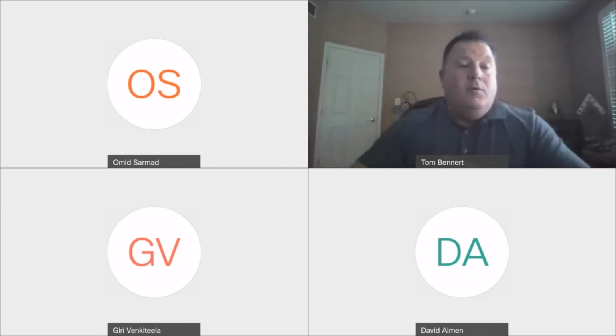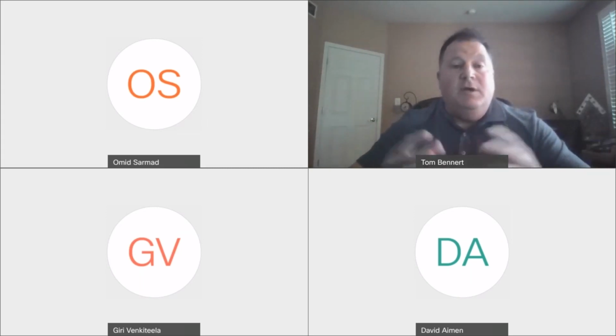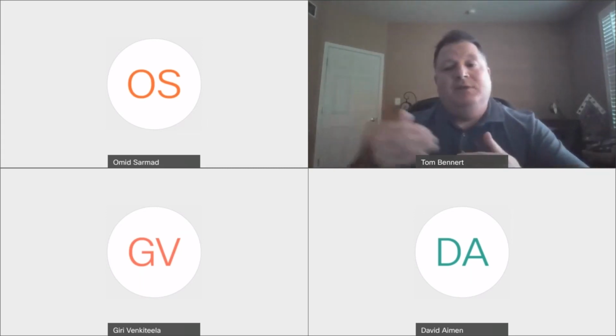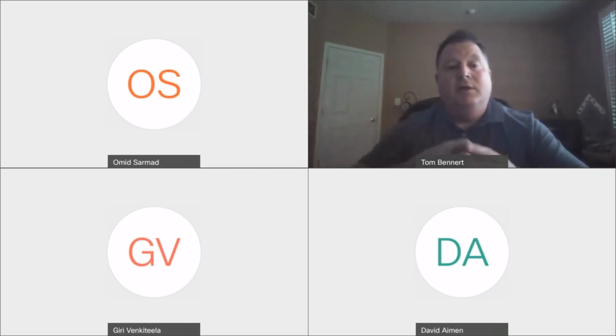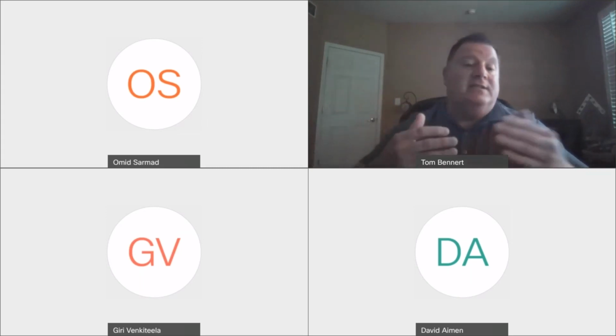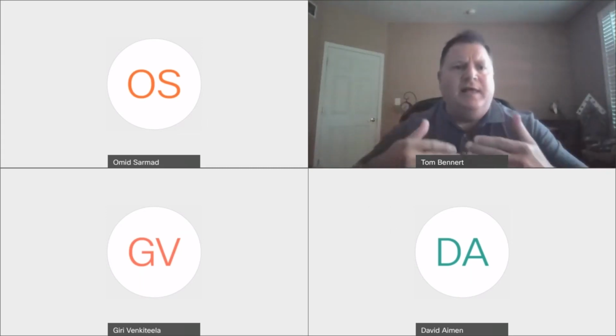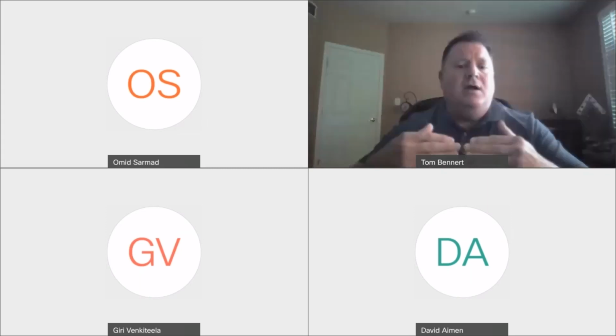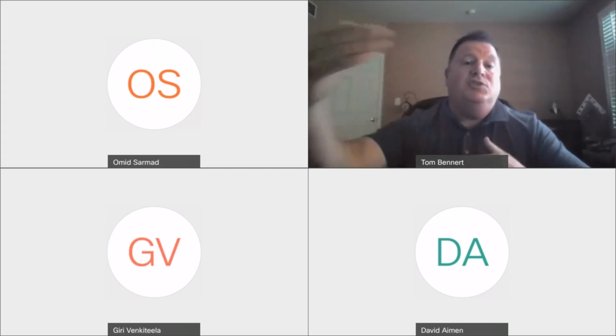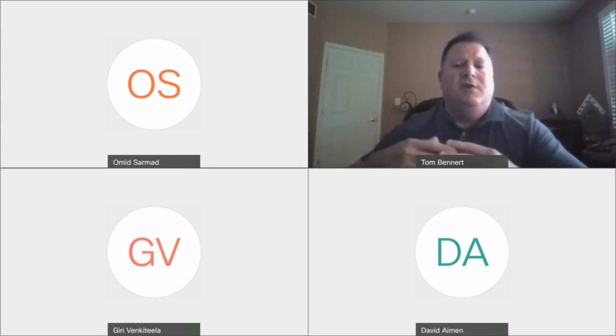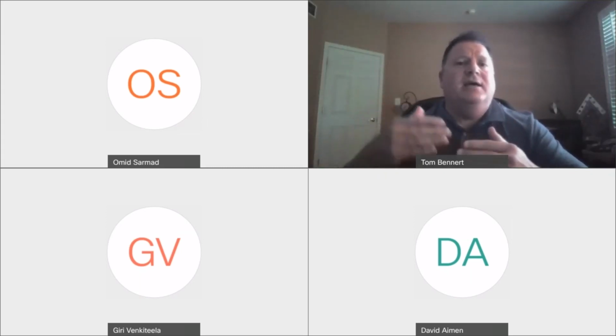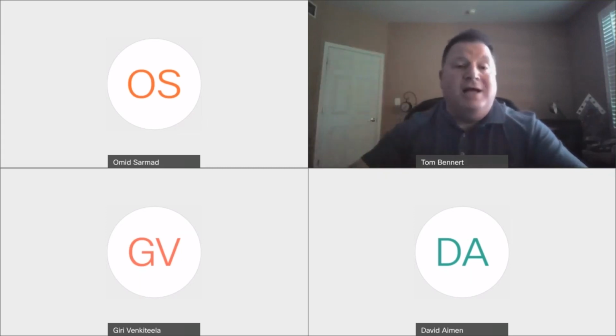Yeah. So there are two things on that side, and that deals with the high temperature performance of the material. We have ways of characterizing the liquid and characterizing the mix. And so we have tests in place and we have thresholds that we know the material should be performing at, or we may have issues in the field. And we actually use those thresholds if we're doing forensic work as well, just to check whether something happened during the construction process, it might have been contaminated somehow, and that allows us to get an idea of whether or not that material failed, or why that material failed.